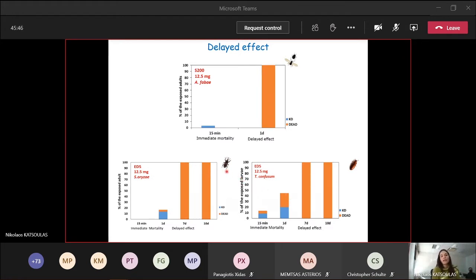Concerning the delayed effect of the silica dust formulations against the insects, in the first graph you can see again that S200 dust proved to be the most efficient at the lowest dose for Aphis fabae, since one day post-exposure to this dust for only 15 minutes, we can achieve 100% mortality of the insects. However, in the other two graphs, you can see that stored product insects achieved high rates of mortality not one, but 7 days after the exposure to EDS dust formulation at the lowest dose.